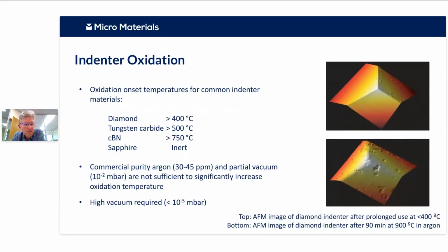As I mentioned on the indenter side, indenters do start to oxidize at different temperatures. And what you can see on the right there is a couple of AFM images that were taken at the University of Cambridge. Here you can see the top one is a Berkovich indenter that has been used for high temperature testing for an awful long time, but at temperatures under 400 degrees, and you can see it's remained pristine essentially, so there's no tip wear. And at the bottom, you can see that one's literally an hour and a half in argon at 900 degrees, and you can see already there's some pitting and some blunting of that indenter.